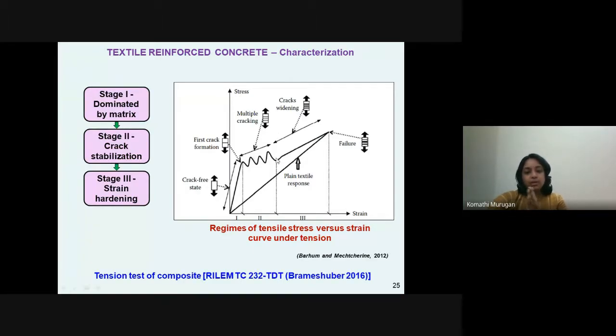At the end of it, we go to the third stage, which is called the strain hardening stage. In the strain hardening stage, the concrete along with the textile in the composite form shows strain hardening properties. At the end of stage 3, the textile, whether it is a single layer or multiple layers, once and for all ruptures, and it starts showing the down peak, and that marks the strength of the panel, the tensile strength of this particular configuration of the textile, number of layers, along with the matrix.